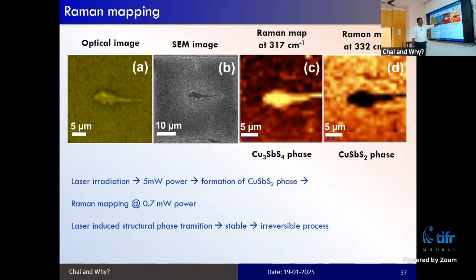So this corresponds to the Raman mapping of two different phases. We irradiated the region, and then we probed it with a low power, 0.7 milliwatt, so that we don't cause further damage. When we plotted it, we see that the center region is CuSbS2, and the peripheral region is Cu3SbS4, which is not exposed to the laser. The exposed layer is CuSbS2. So we can clearly differentiate, and this process is irreversible.